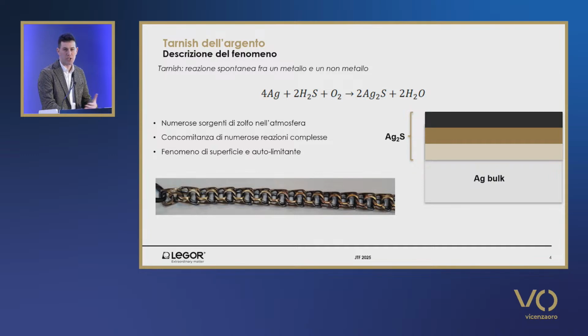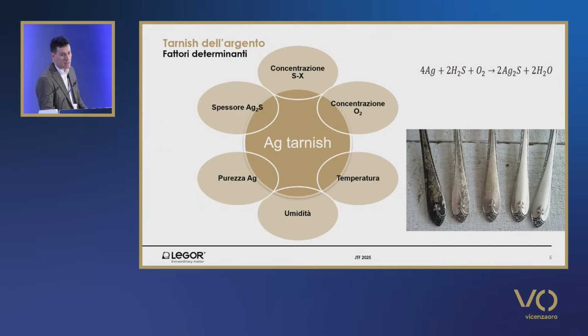Well, we should specify that this phenomenon is a very complex one because it involves a whole series of reactions which take place simultaneously. And the identification of sulfur composites is not enough because there are various composites which intervene in this reaction. Tarnish is a surface reaction. It involves only the first layers of a silver surface, and according to the thickness, there are various colors from yellow to black, which is the real color of silver sulfide.